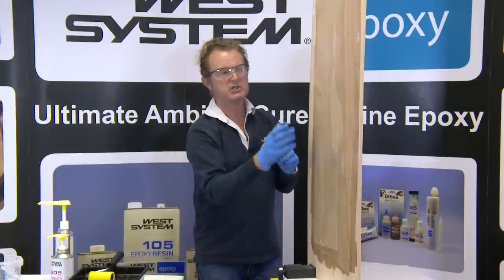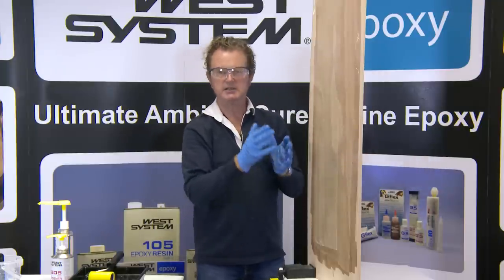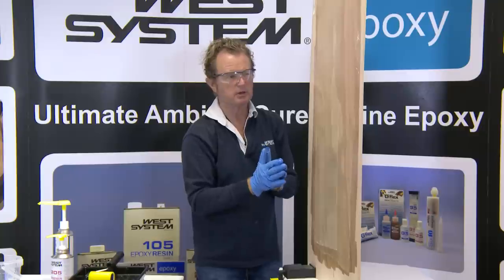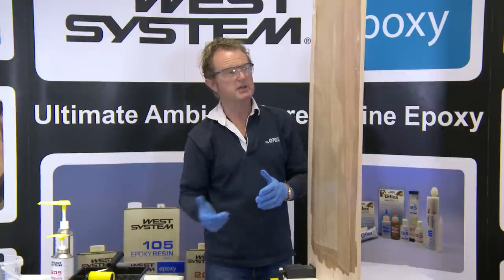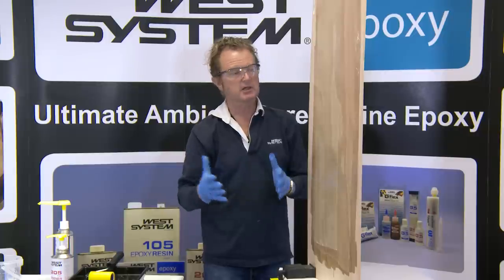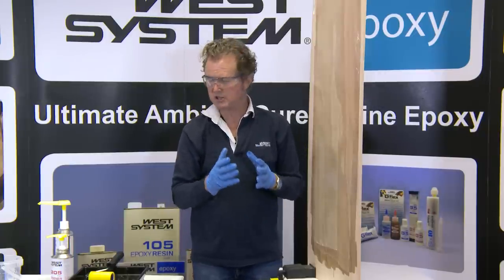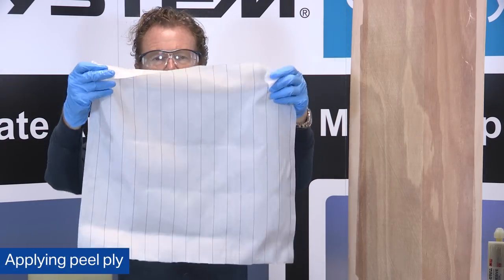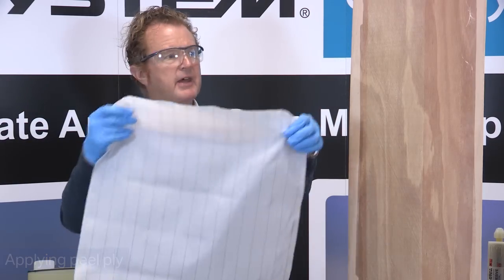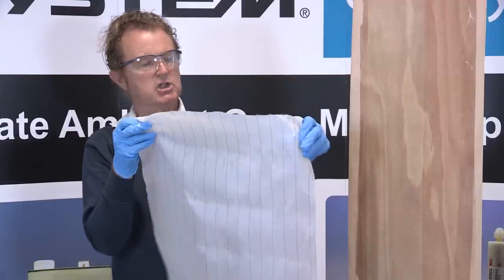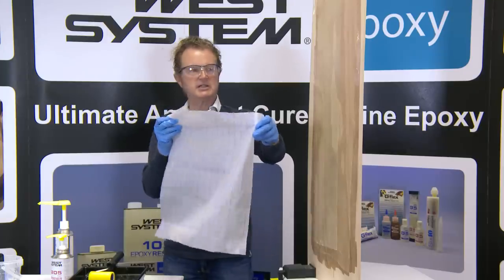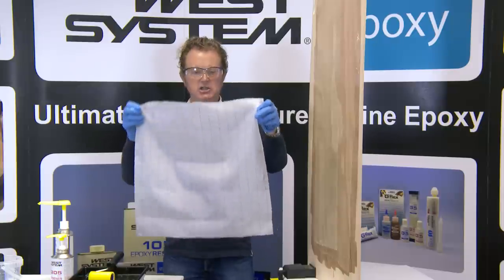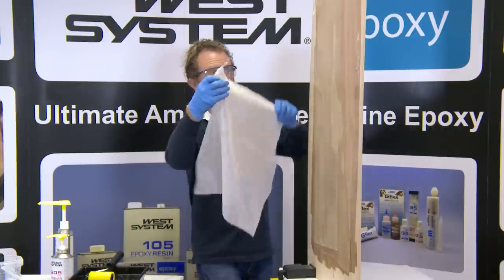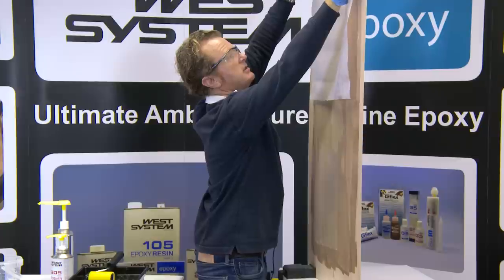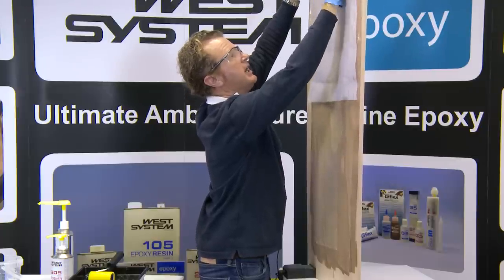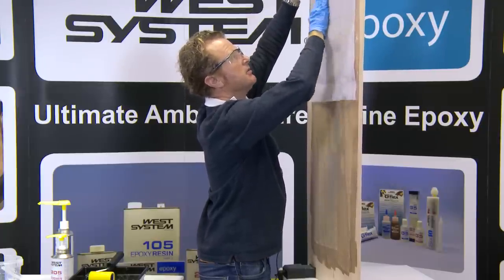With my biaxial fabric, this tends to be for more structural work, and it tends to be underneath surfaces that are painted. I've got a couple of options. I could add more of my epoxy mix to fill the texture of the glass fabric here. Or better still, I can use my faithful friend peel ply fabric, and I can apply that over my glass sheath surface. This will give me a fantastic finish, better than sanding, totally graded so that it's a very, very nice textured surface, and very importantly, any amine blush will occur on the surface of the peel ply.